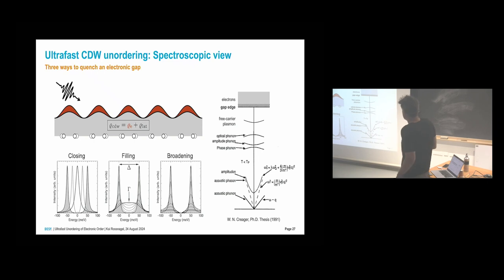And then there are 3 ways to quench the gap. Closing the gap, this would be coherent motion. Filling would be an indicator of incoherence, so you do not move the gap edges, you just shuffle spectral weight inside here and fill the gap. And then you could also think, okay, maybe I have these peaks here, I just broaden them. If you broaden these peaks, then you reach into the gap and also have spectral weight in here. So these are the 3 scenarios we will be looking at, mostly with time-resolved ARPES. And the excitations that are most relevant are the plasmon, phase phonons, and the amplitudon.